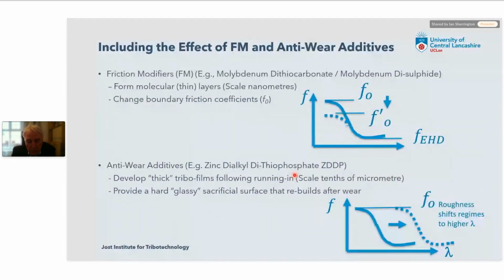Of course, many lubricants contain additives, and two of the most common additives are friction modifiers and anti-wear additives. They work in slightly different ways. So friction modifiers form molecularly thin layers on a surface and reduce the friction coefficient in the boundary regime. So if we look at our Stribeck curve, the low lambda end of this curve comes down.